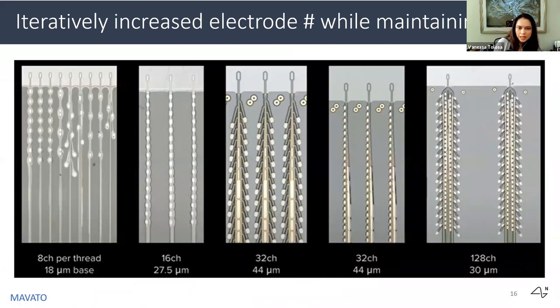So how did we do this? How were we able to fit 1,000 and then 3,000 electrodes in a rat's brain? Here I'm showing you some electrode designs that we made at Neuralink. Each of these threads, with a loop at the tip, is a separate probe that gets inserted into the brain. And each thread is only a fraction of the width of a human hair, which is what you want if you're getting a bunch of these implanted into your brain. The loop is where the robot inserter that we developed at Neuralink can pick up the thread and precisely implant it into the brain.